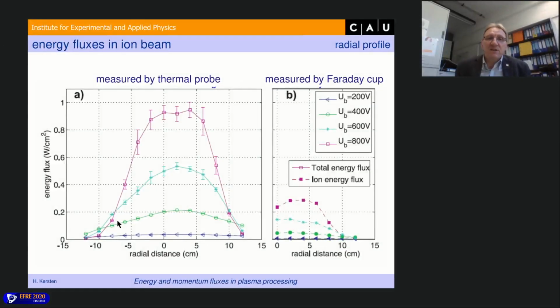And then we measured the radial profile of this ion beam, and the diameter of this ion beam is about 12 centimeters, and this is the center of the beam. And for an ideal ion beam source, you would expect a rectangular profile, but this is a real source, not an ideal one. So this is the radial profile measured by our thermal probe, as you can see here.